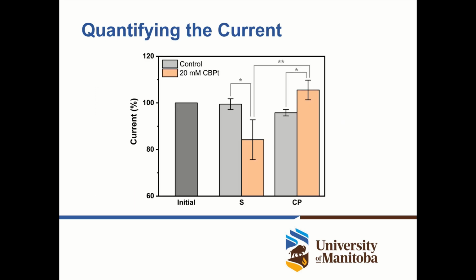We can then quantify the current. When we have our line scans, we can integrate underneath the curve. We can calculate the number of molecules that are being converted at the electrode, and we can plot the current percentage that is represented by these line scans. Here we show one example for a scan rate of 100 micrometers per second across these cells, and we see our initial current value set at 100%.